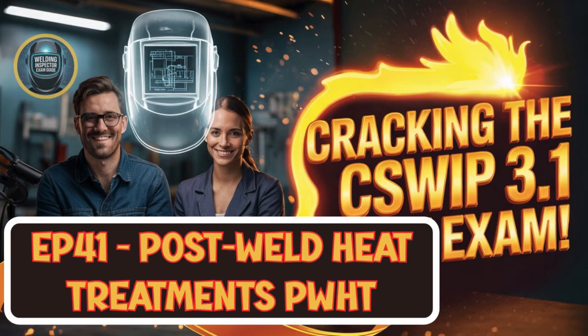Exactly. And beyond the stress, there's the heat effect. The extreme temperature of the arc creates very hard, sometimes brittle zones right next door to the weld. We call that the heat-affected zone, or HAZ. PWHT essentially softens those hard spots, makes the whole area more uniform in its properties, less likely to just snap.